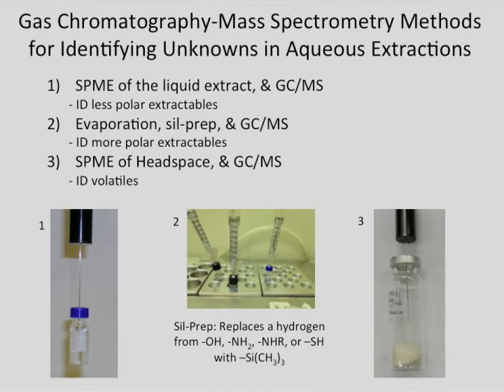This is a SPME fiber, which is — I'm not even going to try and remember what it is. It's a needle, and then there's a polymer-coated fiber that you can hover over the preservation material that either absorbs things that it likes or it doesn't. They come in lots of different forms, lots of different coatings on them. We use 3 of those that are typical and used in our field a lot to do both of these SPME measurements.